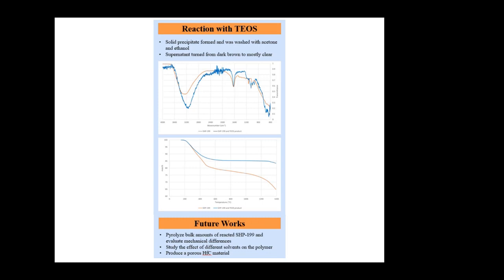We also performed the hydrolysis and dehydration with TEOS. A solid precipitate formed after a few minutes, and a nearly clear and colorless supernatant was left behind, which, compared to the initial dark brown color, is a great visual indicator of a successful reaction. Although we do see differences in the FTIR spectra, the thermal behavior of the polymer and the reacted product is of greater interest. The difference is clear.